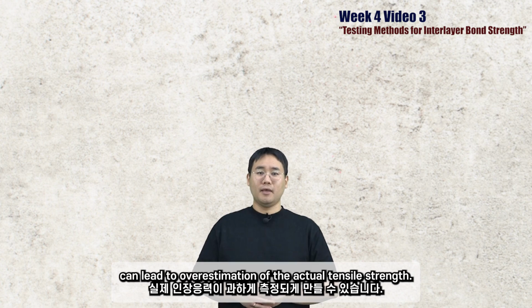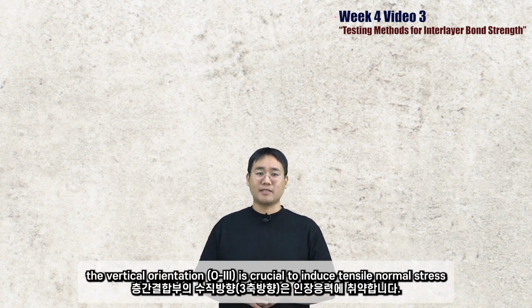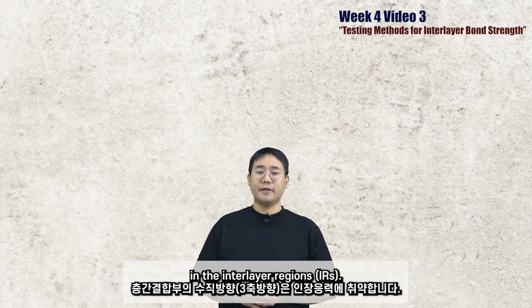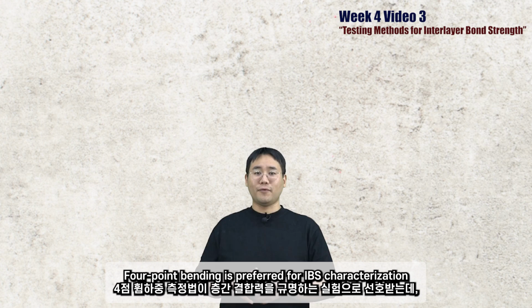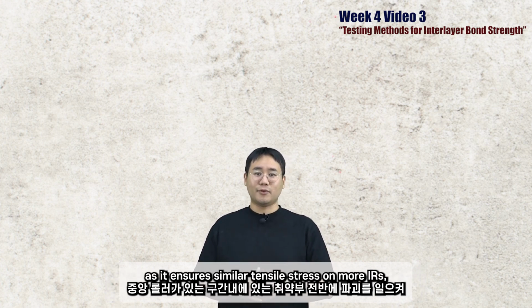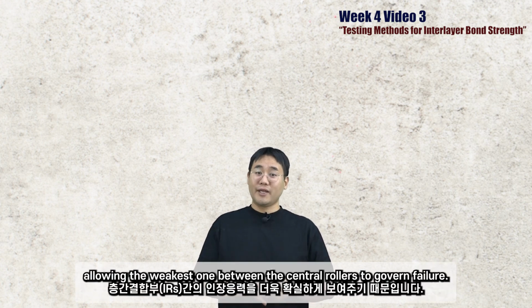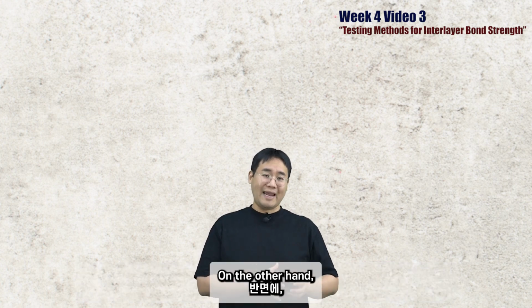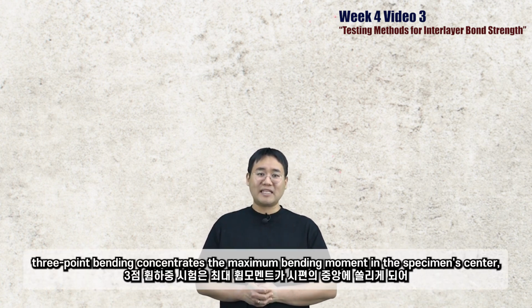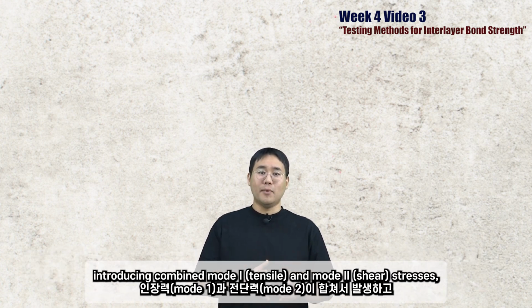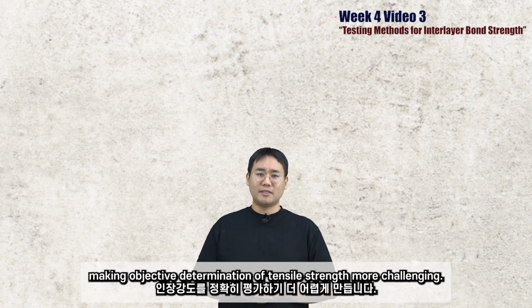However, in quasi-brittle materials like 3D printed concrete, assuming linear strain and stress distribution can lead to overestimation of the actual tensile strength. In bending tests, the vertical orientation is crucial to induce tensile normal stress in the interlayer regions. 4-point bending is preferred for interlayer bonding strength characterization as it ensures similar tensile stress on more interlayer regions, allowing the weakest one between the central rollers to govern failure. On the other hand, 3-point bending concentrates the maximum bending moments in the specimen's middle, introducing combined mode 1 and mode 2 stresses, making objective determination of tensile strength more challenging.